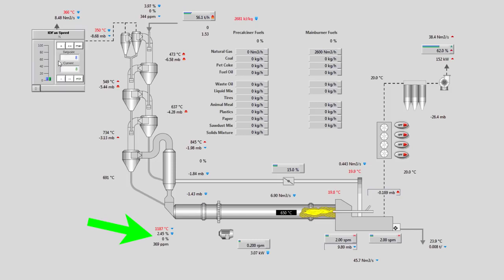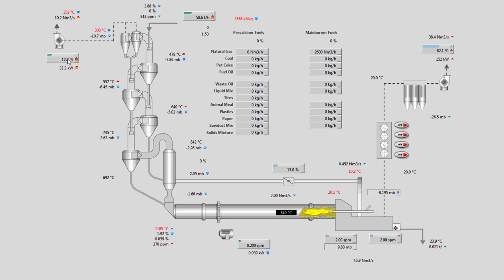And it does drop at kiln inlet. We also generate CO, increase more draft. We see the gas temperatures on top of the preheater coming down, and the O2 going down as well. Let's add more fan. Notice how the temperatures start decreasing on the second stage. The CO at kiln inlet is showing now at preheater exit, though diluted by the fresh air from the tertiary air duct. No need to react.